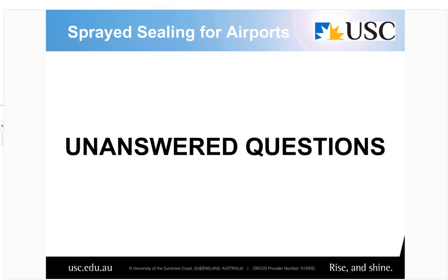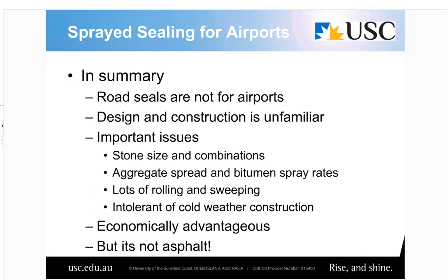Thanks, Josh. I think the key to either of those things is making sure you have a little bit of anti-stripping agent in there, typically 0.5 or 1%. That probably negates most of the question around which one it should be. I think most organisations or authorities allow both these days.